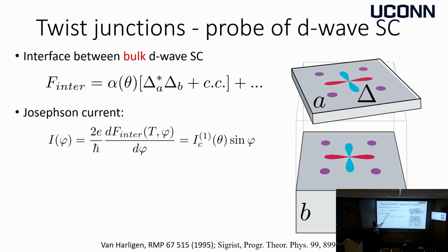So what the interface does is couple the two order parameters describing the two samples, and it allows me to determine also the observable quantities such as the current. And before long, you will notice that if I couple the order parameters in the simplest possible way in Ginzburg-Landau theory, and I calculate the current flowing along the interface, I find the relation between the current and the phase difference. That's the well-known Josephson relation. Unlike the simple case that you see in the textbook, the critical current prefactor should depend on the rotation angle, because it's clear that this picture changes when the top order parameter starts to rotate.